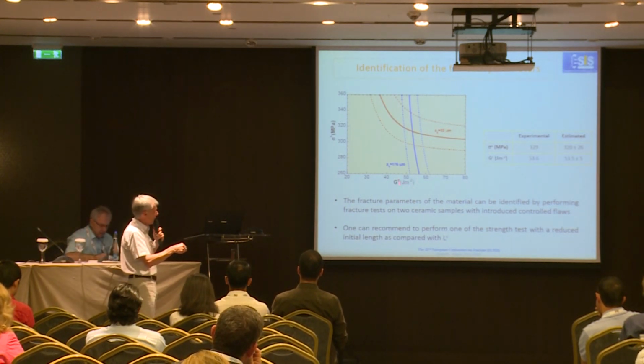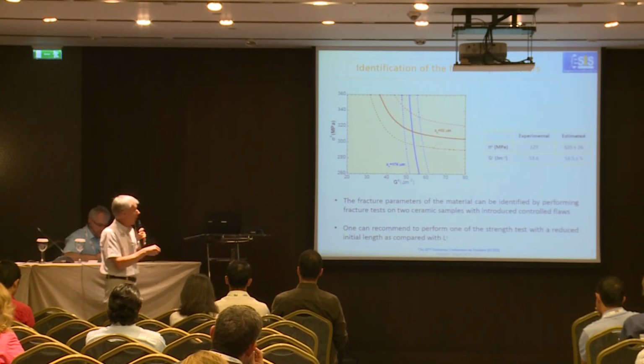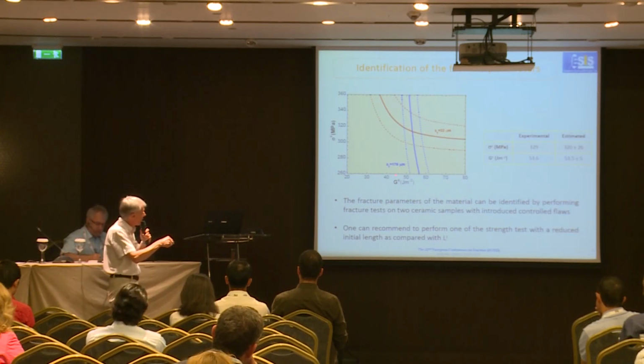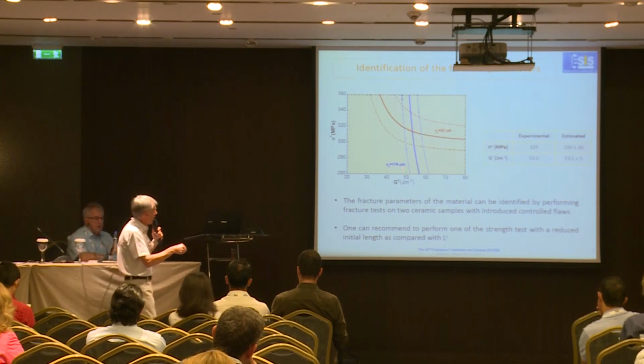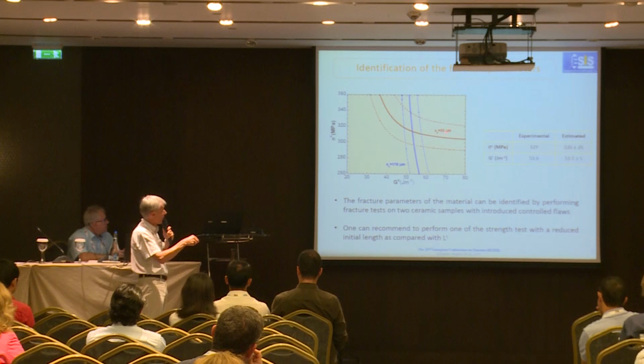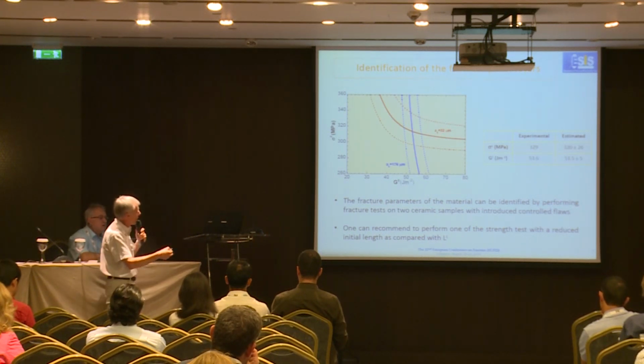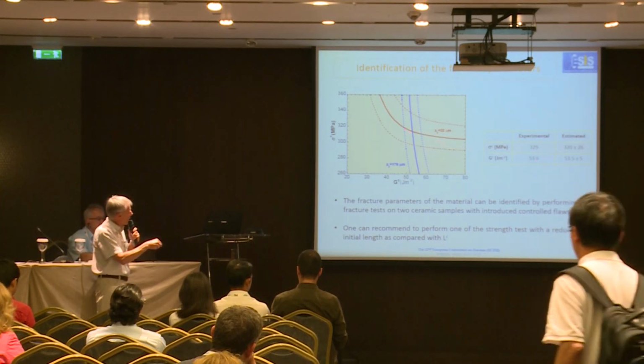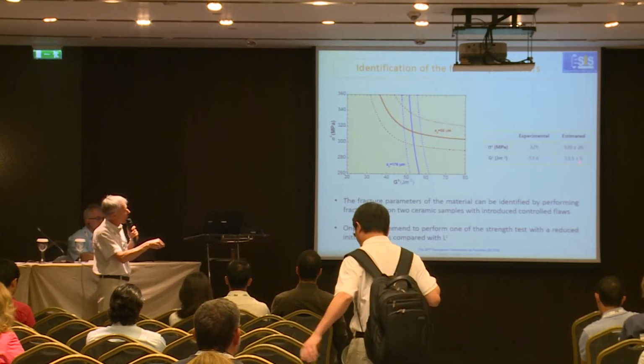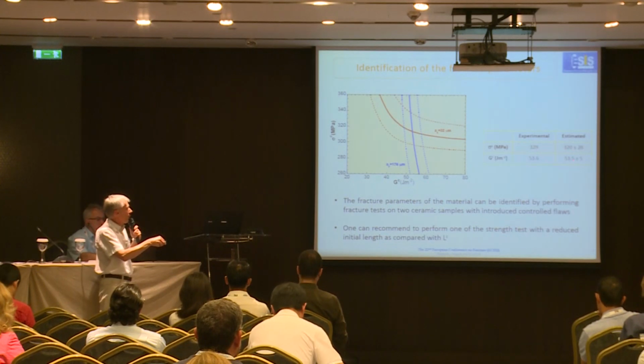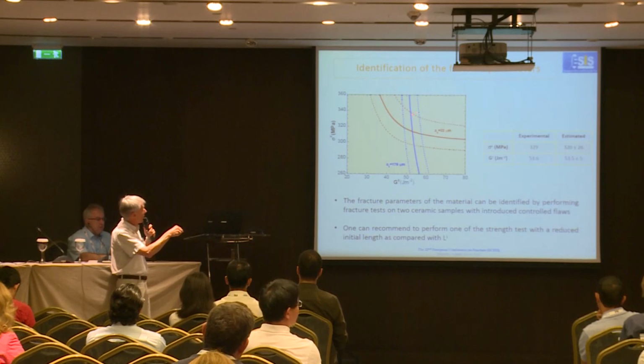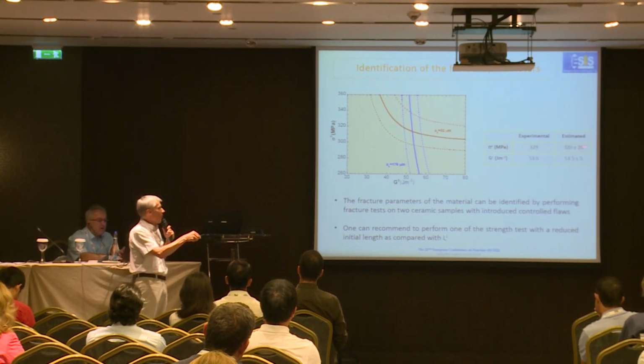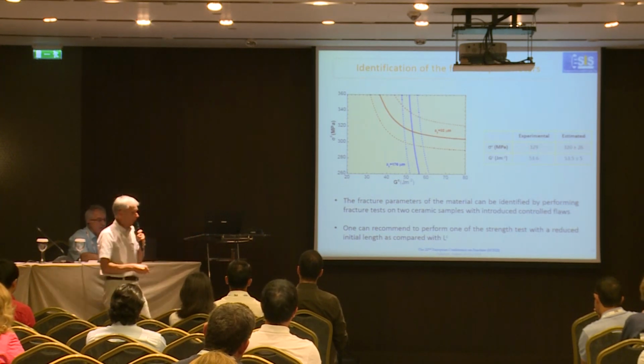which is a plane GC sigma C plotting some isovalues of the tensile strength. That means that each couple GC sigma C here provides the same tensile strength. I have done this for 2 values of the initial crack length of the defect, and the intersect corresponds to the properties of the material. So here you can see that those are the data from Cook, and the estimated data are in rather good agreement. Cook also provided the experimental uncertainties which correspond to the dotted lines. So we can see that we have an amount of uncertainty while estimating those experimental data.